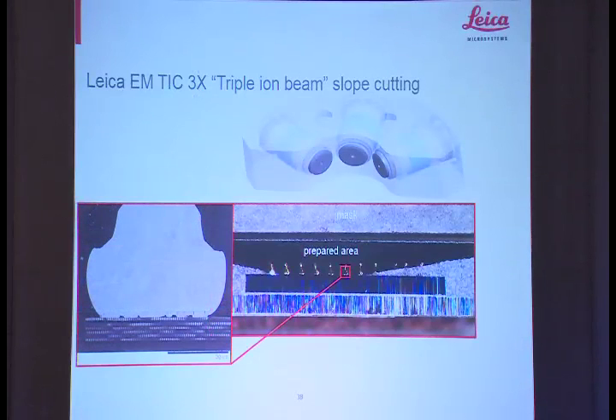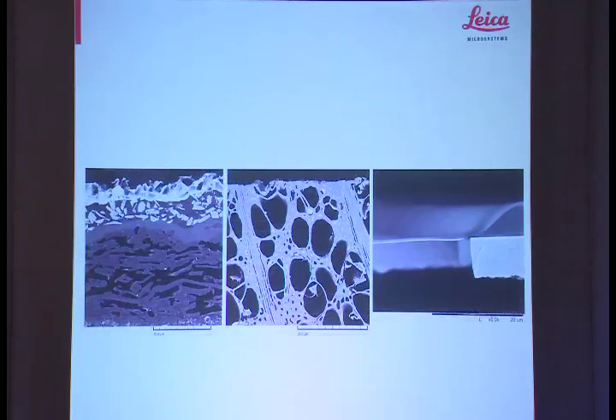Normally used for microelectronics, this is a cross-section of a chip, and this is a gold wire bond inside a chip, and this is a failure analysis technique, so we can see the failure here was the gold wire bonding itself. So this is why the mobile phone failed, or whatever the chip was used for. We can also use this technique for preparing other samples from silicon carbide. This is sandpaper. This is a veneer, and this is a cross-section of an ultra-thin section on a grid. So that's an ultra-thin section, 50 nanometers, on an EM grid, so we can slice very simply through it.